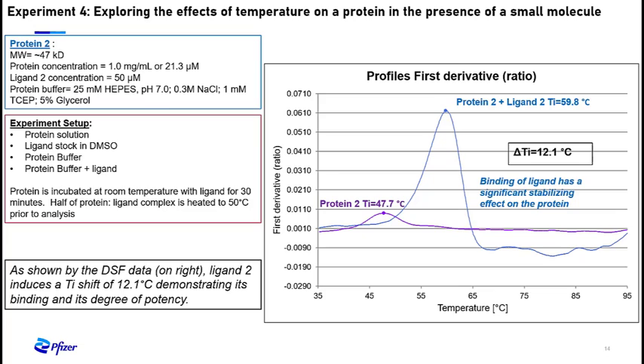In experiment number 4, we will revisit the 47,000 Dalton protein from experiment 2. Here we have the protein at 1.0 mg per ml and have added a stabilizing ligand at a 2:1 molar ratio, ligand to protein. We've taken the protein ligand complex and incubated half of it at room temperature and the other half at 50 degrees centigrade for 30 minutes. On the right is the DSF data showing the protein ligand complex to have a TI of about 59.8.